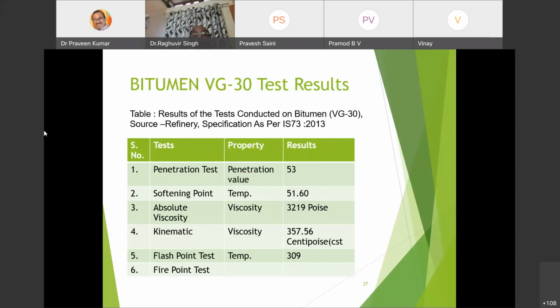The sample is then sent to the in-house site laboratory for relevant tests: penetration test, softening point test, absolute viscosity, kinematic viscosity, flash and fire point, etc. In our case, the VG test results are shown here. The penetration value is 53. Softening point is 51.60, where the minimum requirement is 47 degrees. Absolute viscosity is 3219 poise. Kinematic viscosity is 357.56 centistokes. The flash point test result is 309 degrees.